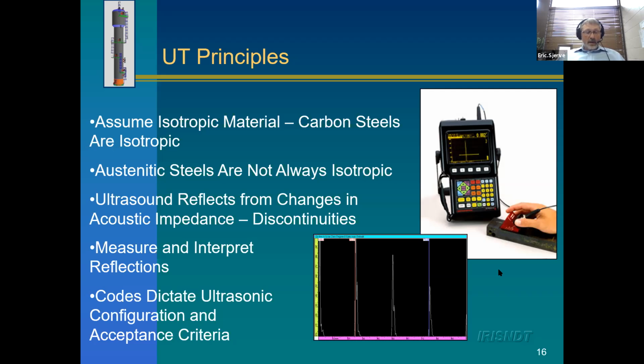With ultrasonic testing, all we're doing is sending ultrasound into the material, so maybe a carbon steel. If there's a defect there, some of the sound's going to reflect back. So that sound reflects back to our transducer. We see a signal, and the codes tell us how to interpret that signal as maybe a discontinuity that's not going to lead to failure, or maybe it's a defect that needs to be repaired. So that's what we're doing with ultrasonic testing.